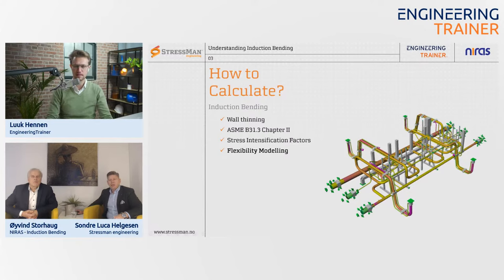In this case also, you can see that these bends here are not 90 degrees, for example. These are bent to what suits the system the best. And what we did here, when you're going to code check it, you don't need to do any hand calculations with regards to stress intensification factors, nor with regards to the pressure containment, if you're using B31.3, of course. That's an important thing. If it's different codes or regulations, there might be different ways of looking at it. But from a B31.3 perspective, that's no problem.